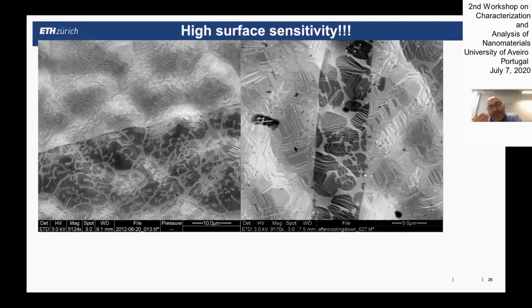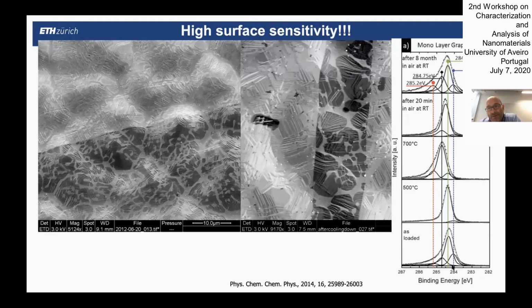And when we heated up the sample, the contrast of graphene got again uniformly dark. What we realized by doing some in situ XPS measurements at the beamline, we saw from the XPS carbon K-edge position that the contrast in the SEM actually changed because the coupling state of graphene on the copper has changed. The coupling after growth is strong, but when you take the sample out, expose it to air, after some time, oxygen intercalates and the coupling changes. And this change in coupling strengths we can visualize in the SEM and measure by XPS.